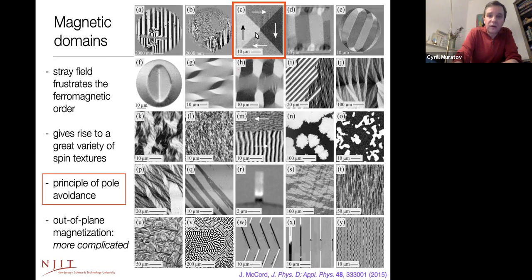Indeed, since the magnetization is piecewise constant, the distributional divergence is just concentrated on the jumps of the magnetization, and it is given by the jump of the normal component of the magnetization along the jump. So you can see that in all of these four discontinuities, the normal component of the magnetization remains fixed. And similarly, at the sample edges, the magnetization is tangential, and therefore there is no normal component, and there is no jump of the normal component.